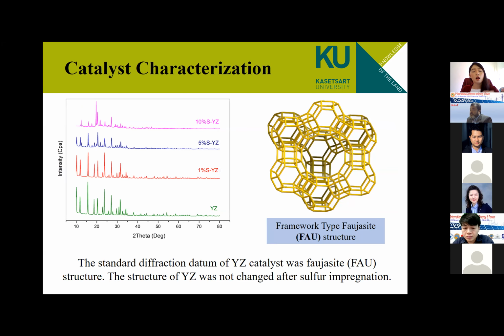As you can see from the picture, the standard diffraction diagram of the YZ catalyst shows the crystal structure. The structure of YZ was not changed after the sulfur impregnation. The sulfur impregnation reduces the diffractogram peak by sulfur infiltration into the catalyst structure.